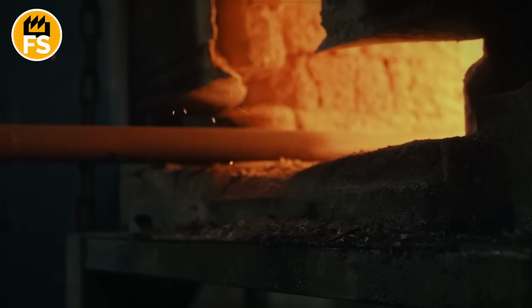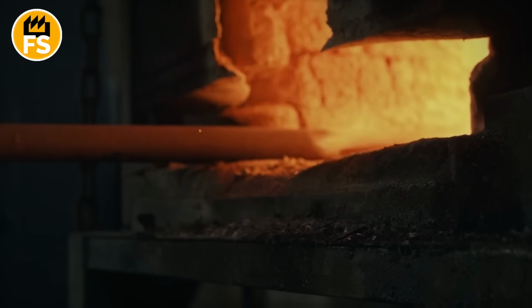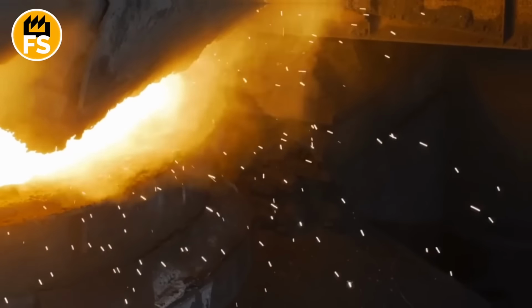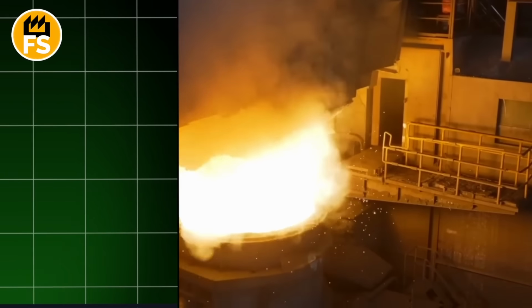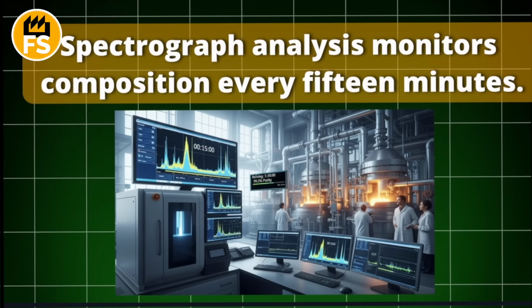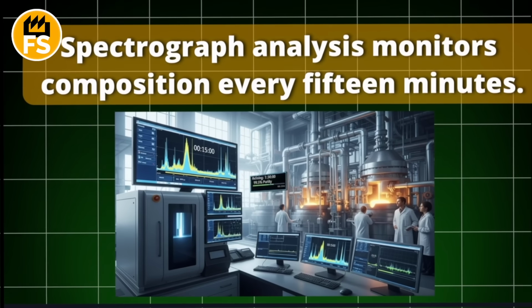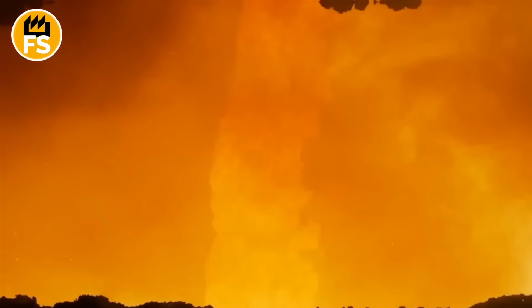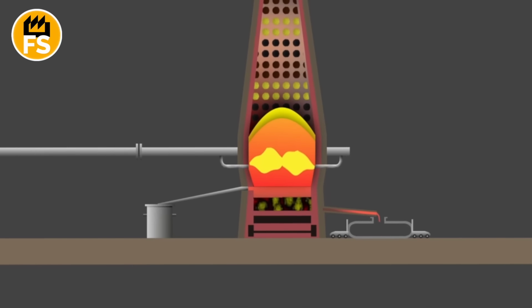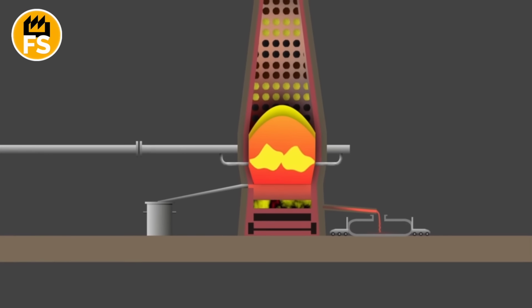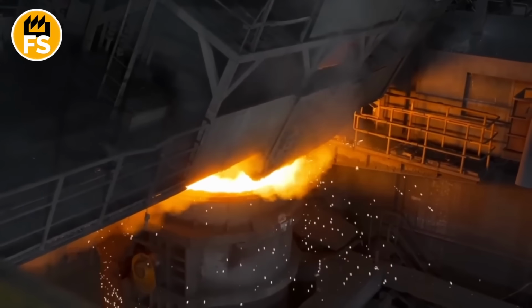The resulting charge is refined, purged with argon to remove gases. Flux is added to clean out impurities. Spectrograph analysis monitors composition every 15 minutes. Refining takes 1 to 2 hours, bringing purity up to 99.5%. The finished ferromolybdenum, a silvery melt, is poured into molds for briquettes weighing 2 to 110 pounds.